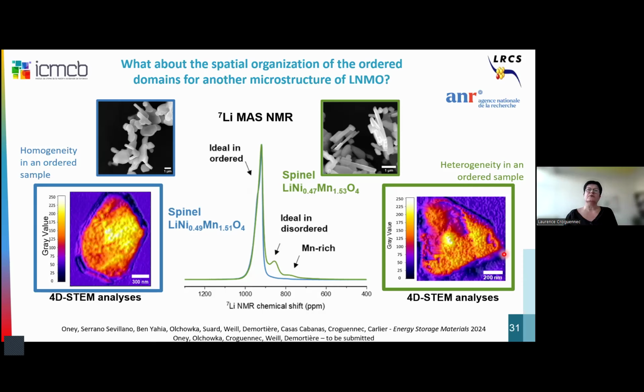So here I wanted to highlight another result that we obtained very recently in collaboration with LRCS, Arnaud Demortière. These platelet particles here, LNMO, were obtained under different conditions in molten salts as thin platelets, in order to be able to use the 4D-STEM analysis and to do cartography on the platelets, to localize ordered and disordered domains. For these particles here, we have a material very close to the stoichiometry, and as shown here in blue by this lithium magic angle spinning NMR spectrum, we have a single signature for lithium in this material, in good agreement with an almost perfectly stoichiometric material.